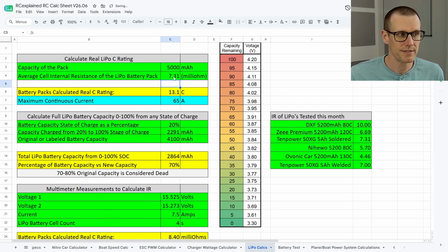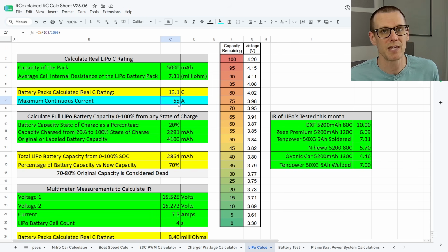And the soldered cells at 7.31 show us a 13.1 C rate and the maximum continuous current being 65 amps. Now keep in mind, this is a pouch cell, and that pouch cell has a lot of surface area to get rid of that waste heat, where these cylindrical cells do not have that surface area. So it's going to be lower here, and I recognize and understand that.